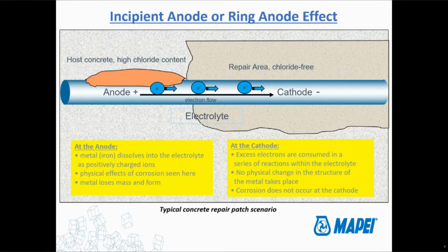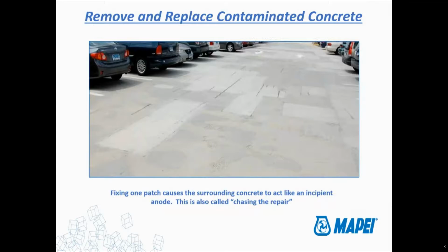So what happens is we'll call it chasing the repair. You do this repair area, and then 2 or 3 years later, you'll get the call, and they'll say, "Hey, you did that patch, but now it's just corroding all around the patch. It's just all cracking and falling apart. What's going on?" Well, what's going on is we've created this big giant drop in potential between the repair area and the existing area, and that's ripe for creating a new corrosion cell immediately outside of the patch. So we call that chasing the repair.